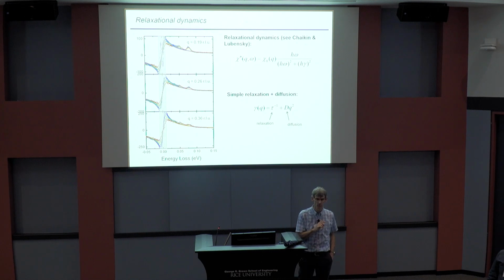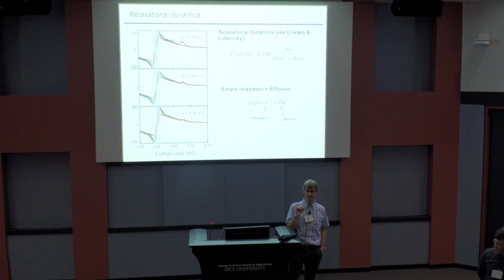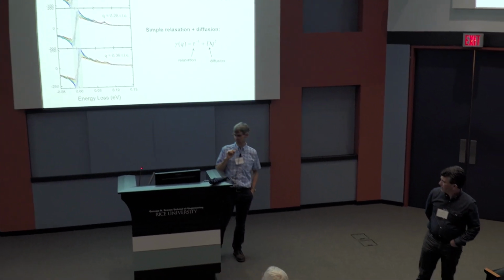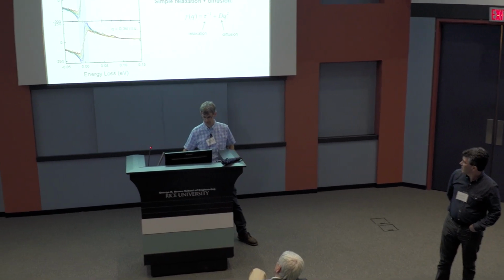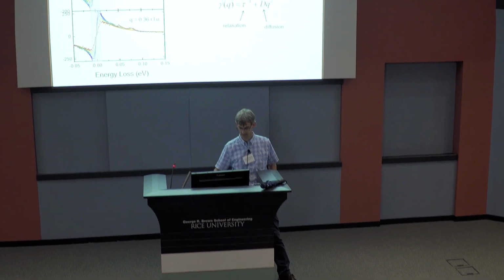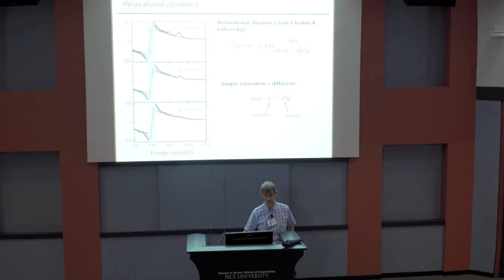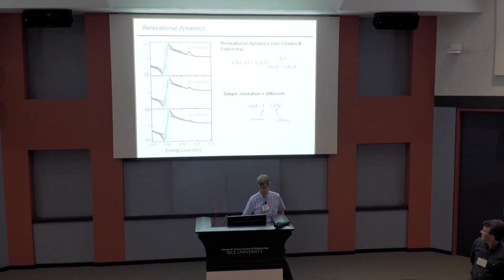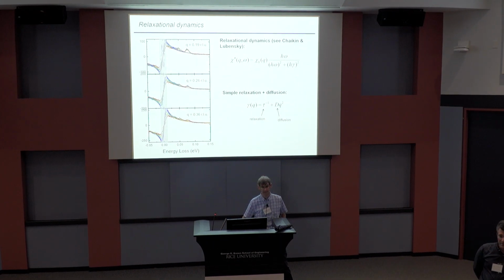They're similar. So in that range, would you expect that you still have frequency dependence of your scattering rate? Oh, and we do. Well, the response is frequency dependent. The scattering rate is constant. And so this is the point. The frequency dependence comes from this, and then the tau is just in this gamma. So we don't need to invoke any additional frequency dependence in that.